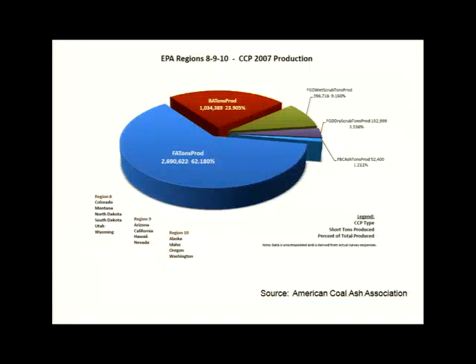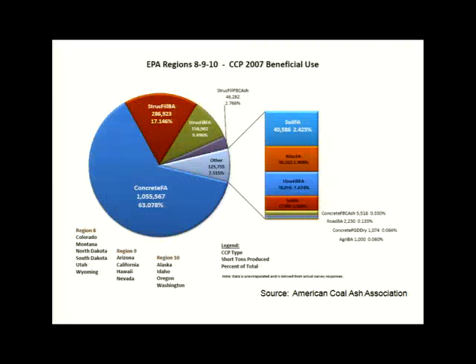Looking a little bit more specifically, this gives you an idea for EPA Regions 8, 9, and 10, which does include Oregon. It shows you the coal combustion product production in 2007. The large blue wedge there is the actual fly ash tonnage produced. And then it shows how much of that fly ash in Regions 8, 9, and 10 was actually used in beneficial applications. One of the main things we use it in this region is concrete production, putting that fly ash into concrete to make it a better material.